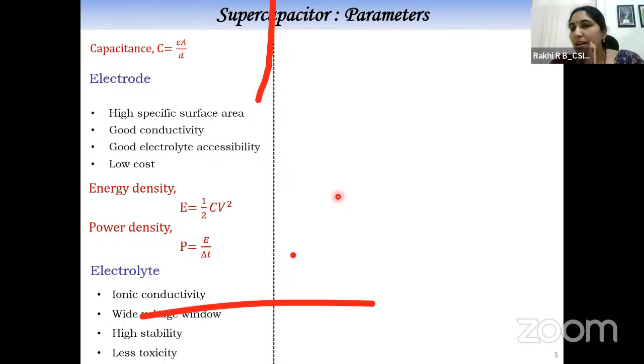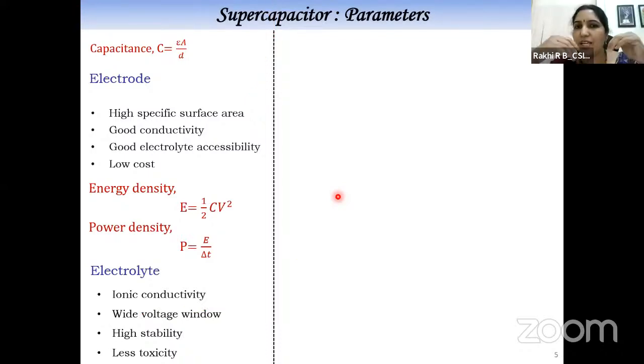Okay. For a lab scale electrolyte, we are using a water-based system. There the potential window is limited to 1.2 volts, whereas we can go for organic electrolytes, and we can extend the potential window up to 2 or 3 volts. And if you are using ionic electrolytes, we can extend the potential window up to 4 to 5 or even 6 volts. But for lab scale applications and the initial level of testing, we stick with the water-based electrolyte system.